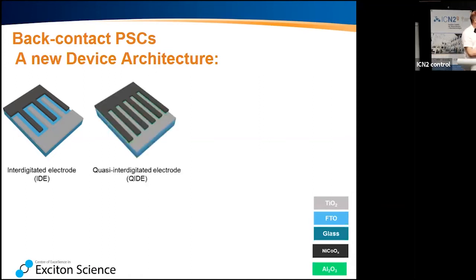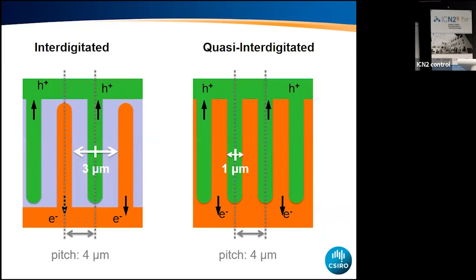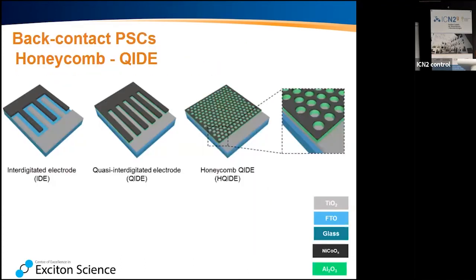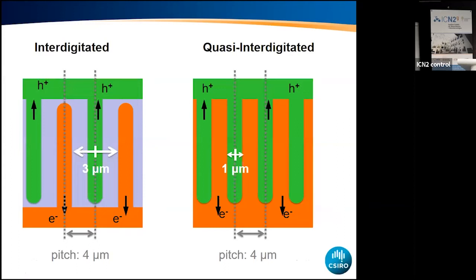We changed that configuration a little bit, and now we have a non-patterned electrode below. This one is collecting the electrons, and then we only have one set of fingers. First of all, we put an insulator on, and then on top another finger which has the second electrode. You can see this slightly greenish shaded layer underneath. That's an insulator, and on top of that comes the single finger, which is the hole collecting electrode. So we refer to that as quasi-interdigitated.